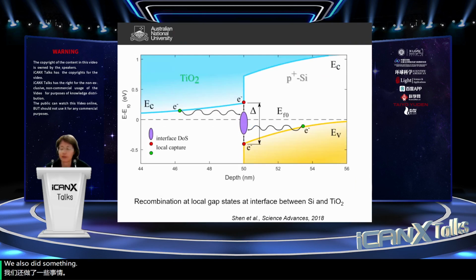We also did some simulations to understand what was going on, and we found that what can happen is that depending on the band offset, that delta there, capital delta, if that is about the right size, you can actually get tunneling of electrons and holes to interface states at the interface between the titanium dioxide and silicon. And so you can get recombination exactly at the junction. So rather than having to add an extra recombination layer, you can actually get recombination directly at the interface and avoid those extra losses with that layer.